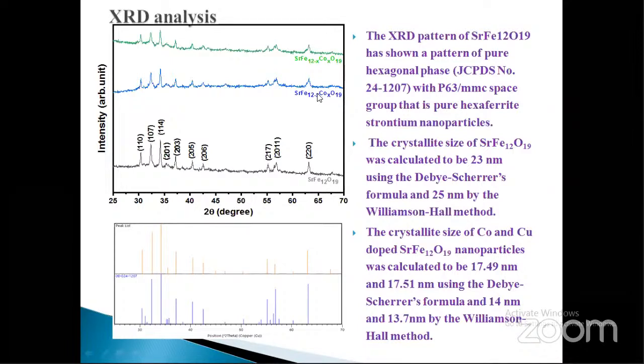and this is for cobalt doped. Pure hexaferrite strontium nanoparticles were formed with space group P63/mmc, and the crystallite size of strontium hexaferrite nanoparticles was found to be 23 nanometer for the undoped sample, 17.49 nanometer for cobalt doped, and 17.51 nanometer for copper doped, calculated using the Debye-Scherrer formula. All the patterns matched well with the standard JCPDS data.